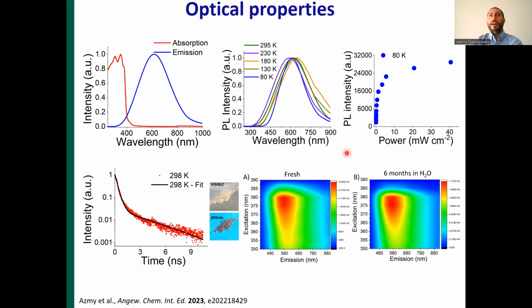We wanted, however, to identify whether this emission stems from self-trapped excitons or permanent defects. And for that reason, we performed variable power PL studies. And as you can see, with increasing the laser power intensity, the emission saturates at higher power flux. This means that the emission stems from permanent traps and not self-trapped excitons, because the number of traps is finite, and by increasing the power density, the traps are filled, and therefore they cannot contribute further to increasing the emission intensity. And for the record, this is one of the very rare cases where the broad light emission in this class of materials is ascribed to permanent defects and not self-trapped excitons.